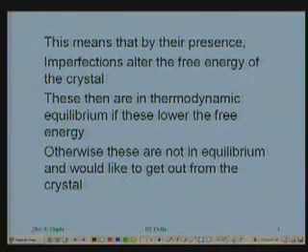So, if they lower it and bring it to a situation where for that configuration I have the minimum free energy, it is stable equilibrium, and these imperfections are in thermodynamic equilibrium. Otherwise, these imperfections will not be in thermodynamic equilibrium and therefore would always have the tendency, wherever or whenever they get a chance, to get out of the crystal. Okay?